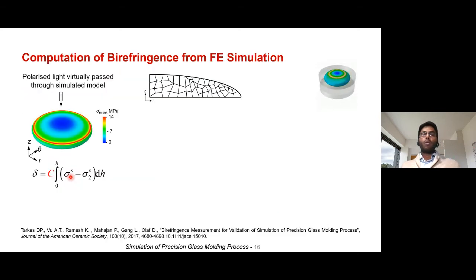And now what is the next set of tasks for us? We have residual birefringence information from the experiments. We have finite element simulation where you can compute residual stresses, but you cannot compare both of them. You need birefringence also from the finite element simulation so that you can compare with the experiments directly. So how do you do that? Generally the simulation is axisymmetric, as I mentioned in the past slide. This shows a revolved 3D model of it after we do a 2-dimensional axisymmetric analysis. So this is what we get from the finite element simulation.